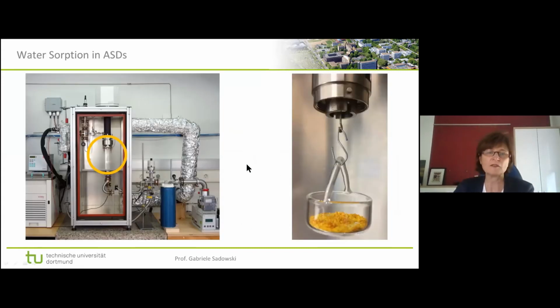And then we measured the water sorption. So this is a homemade water sorption apparatus here. We have an equilibrium cell. This is where we have our spray-dried formulation, and they are hanging on a hook, and the hook is connected via a magnetic coupling with a balance. So on top of this, this is actually the balance. So this sample is hanging on a balance, and the whole thing can be kept at a constant temperature.